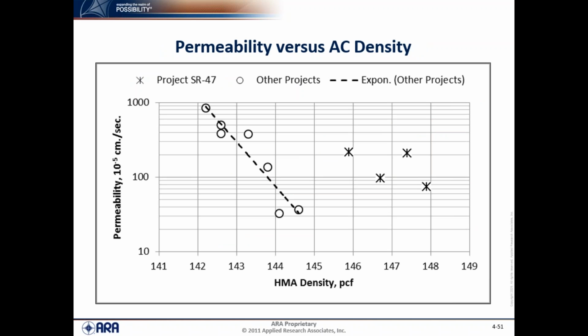Now, coming back, when we started looking at the data, we looked at field permeability versus air voids, and macro depth or texture depth versus permeability and air voids. Initially, it was kind of all over the place. But one thing we did see consistently, and this comes back to what I noted about the difference on State Route 47: if you look at the open circles, the other projects, there's a reasonable correlation on average between the HMA density and the field permeability test right after sealer application, kind of time zero.